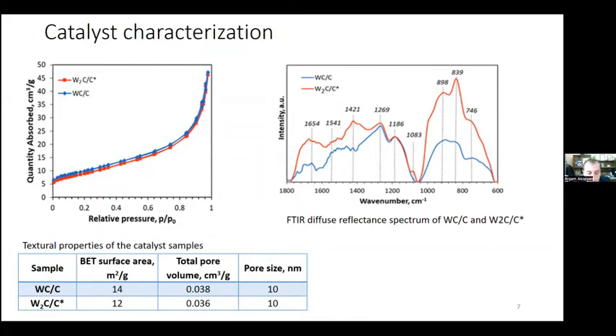In the infrared spectrum, there are peaks attributed to stretching vibration of WC, stretching modes of tungsten oxide vibration, and there are also peaks attributed to the vibration of quinone groups and the peaks attributed to the stretching vibration of C-C bonds.